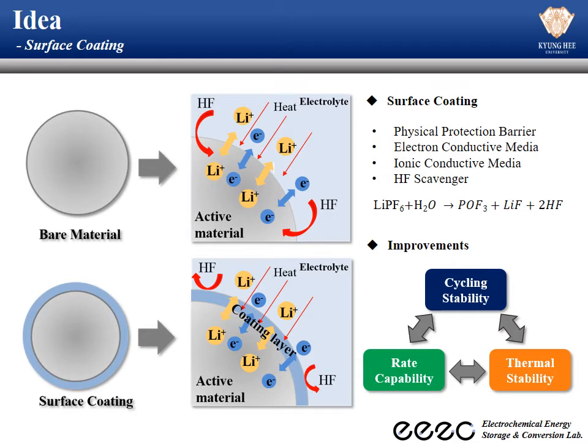Therefore, in order to overcome this disadvantage, a method of forming a coating layer on the surface was selected. When a coating layer is formed on the surface of the active material, it can act as a physical protection barrier from external elements, and ionic conductivity and electronic conductivity can be improved depending on the material constituting the coating layer. In addition, it acts as a membrane that protects against hydrogen fluoride generated through the reaction between LiPF6, a lithium salt in the electrolyte, and residual moisture, preventing structure collapse of the active material that can be induced by hydrogen fluoride. Through this, cyclic stability, thermal stability, and rate capability can be improved.